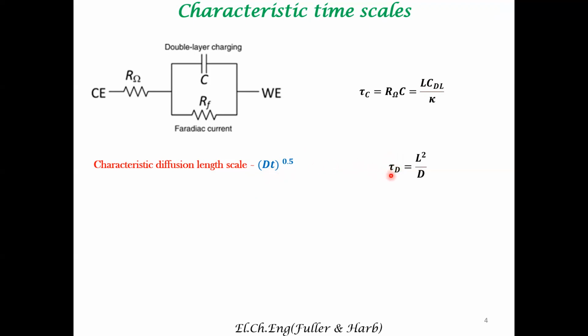characteristic time constant for diffusive processes. This kind of expression you might have seen when you differentiated ballistic motion as against diffusive processes in your mass transfer or transport phenomena classes. So anyway, this is the characteristic time constant for diffusive processes, and we want to compare these two. The objective here is we have got an expression for two time constants, one related to capacitative processes, another related to diffusive processes. We also saw this relationship when we discussed the Cottrell equation, wherein current was proportional to 1 by root t. If you go back and look at that analysis, we never took into account the capacitative current while deriving the Cottrell equation.